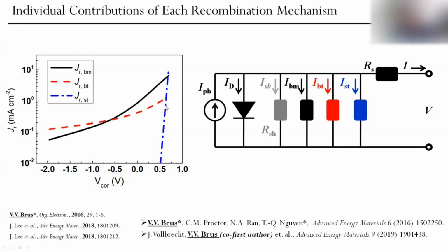For instance, here you see this blue dotted line. It's recombination caused by surface recombination at the interface between the active layer and electrode. And this is interesting because it contributes only very close to open circuit voltage. You see, only at large voltages. However, its contribution at smaller voltages or at negative bias is negligibly small, so we can neglect it. And this sharply and targetedly reduces only VOC. However, short circuit current, which is measured at 0 volt, is affected by other mechanisms.